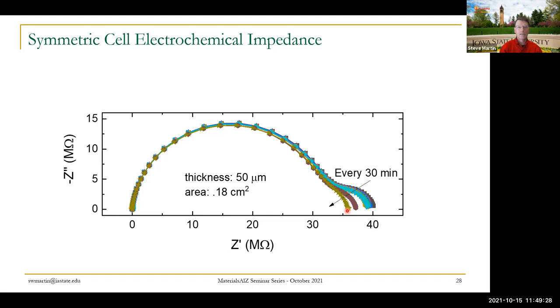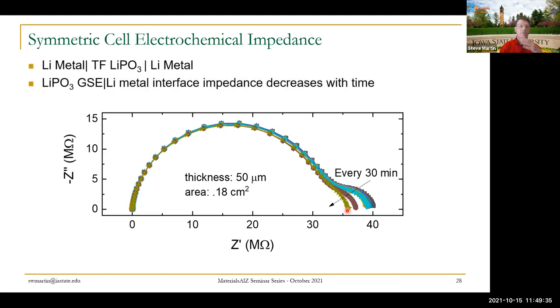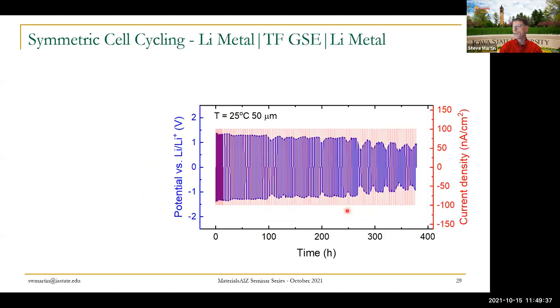My students are making these impedance measurements. As expected, the oxide glass is stable. It's kind of a low conductor, but it just means we can do these measurements on our oxide glasses. We can cycle the glass. There's a little bit of variation you see here, but it gets better. Remember, the impedance is decreasing, so the voltage required to generate that constant current is smaller. And there's a little oscillation here.